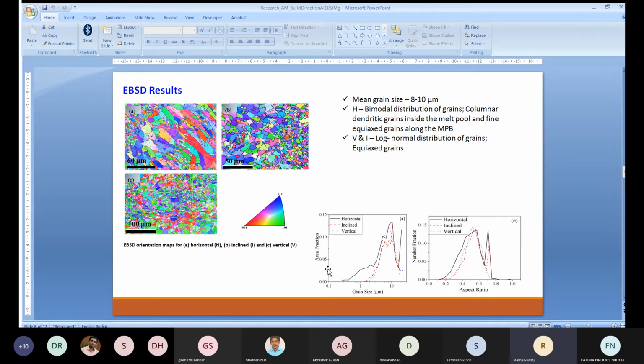And we didn't leave it there. We have plotted the grain size versus area fraction, and the grain aspect ratio, like length versus height, with the number fraction. If we see both cases, we see a bimodal distribution and a larger amount of very fine grain sizes in the horizontal direction compared to the vertical and inclined directions. So you can see the curve here.